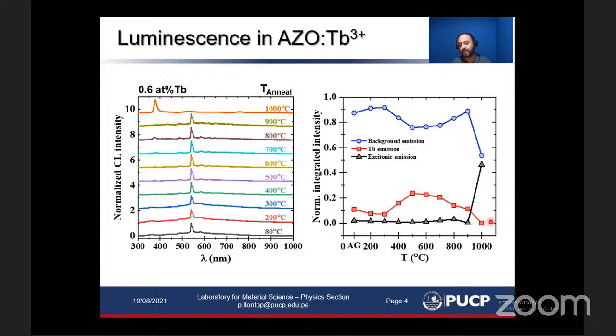And if we increase the temperature up to 1000 degrees, the terbium related emission goes down to 0, while the excitonic emission strongly increases and is almost as equal as the background emission. So high temperature may improve the crystallinity, but may worsen the symmetry of the crystal field surrounding the terbium ions that is required to activate the emission. So the consequence of this is this quenching.